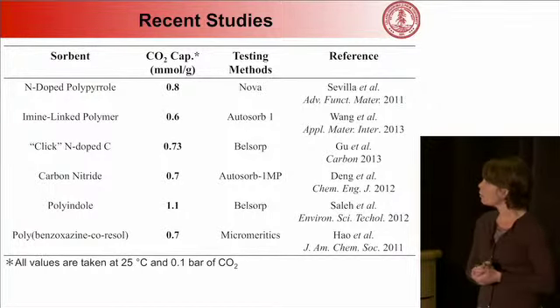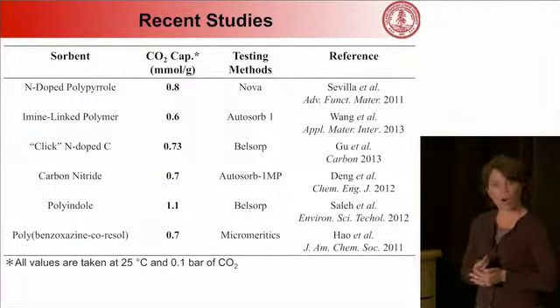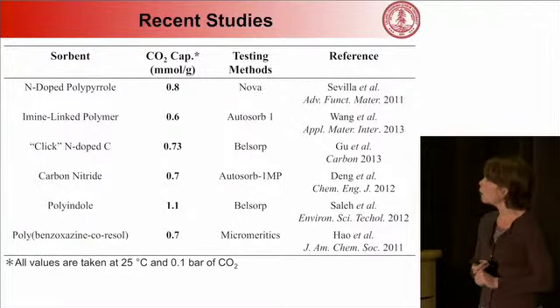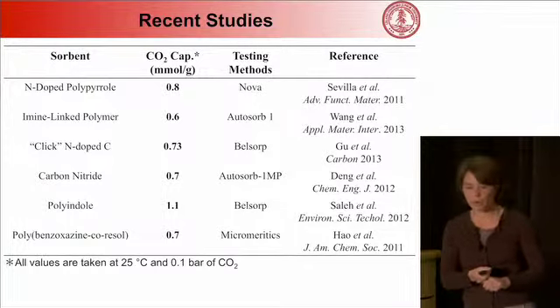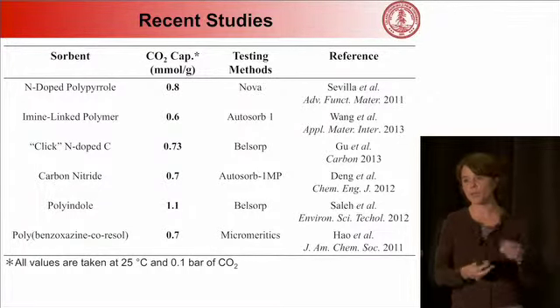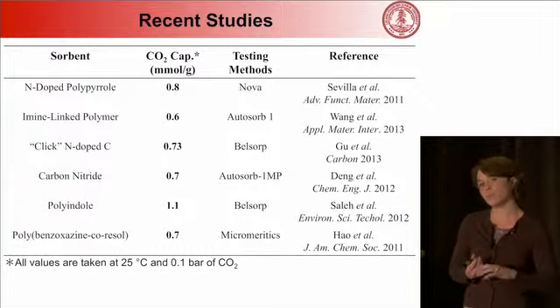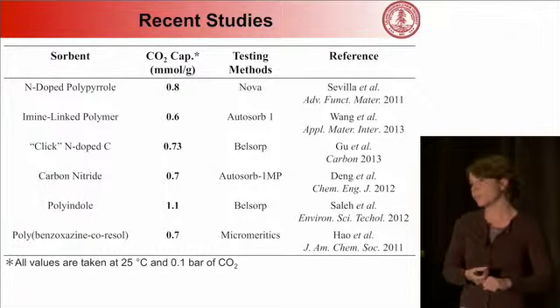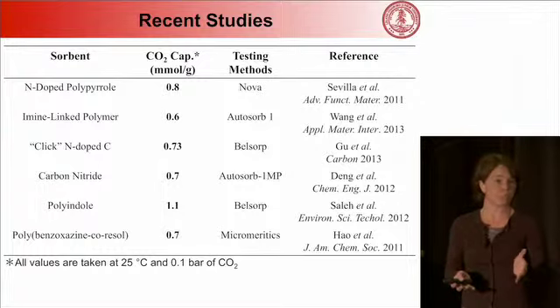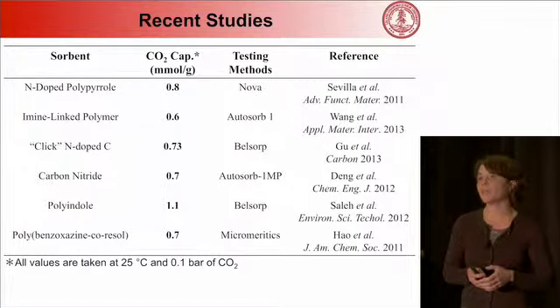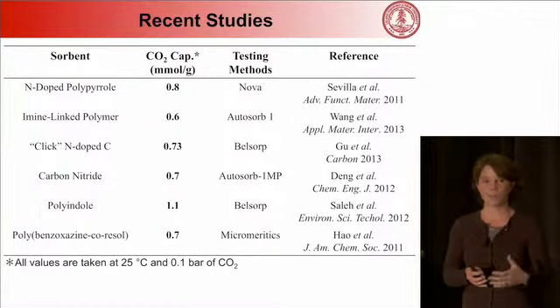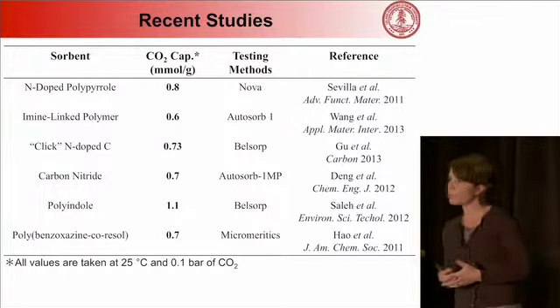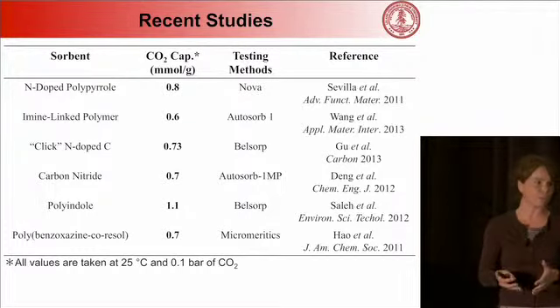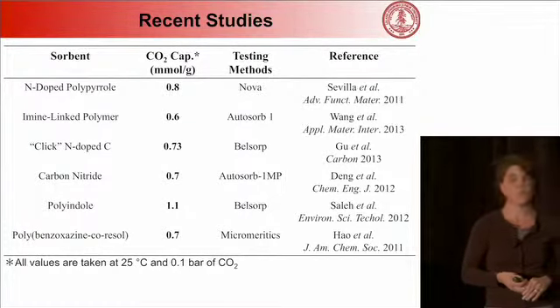So just to recap a little bit of the recent studies that have been carried out before our work, this is strictly looking at nitrogen carbon substrates and sorbents for CO2 capture, and then looking at the different capacities that these materials have. And this is at 25 degrees C and 0.1 bar. It's important to recognize these conditions. As I mentioned in the introduction and the motivation, we're interested in both coal-fired power utility applications and natural gas. So in coal-fired power utilities, 1 bar is the pressure condition, but CO2 is only about 10 to 14% in terms of concentration. So the appropriate pressure to look at would be 0.1 bar. If we wanted to apply this to natural gas, then we would want to look at 0.4 to 0.6 bar, because the CO2 is more concentrated in that system.